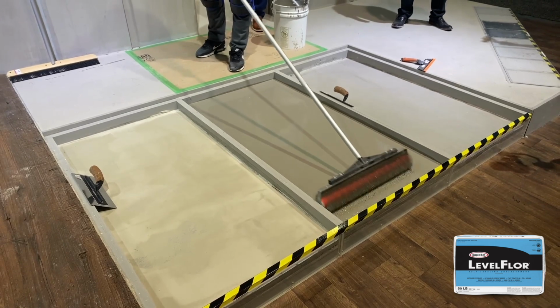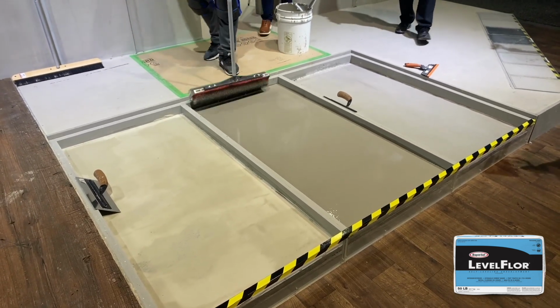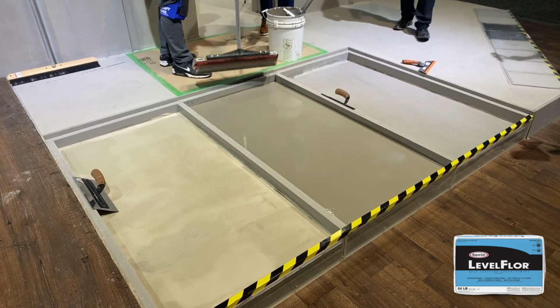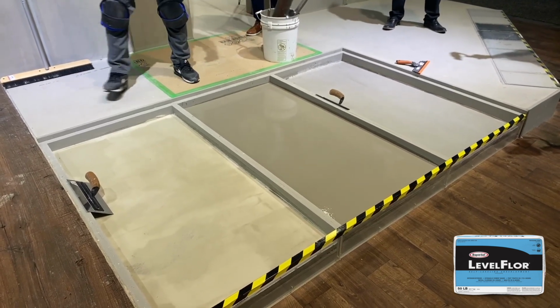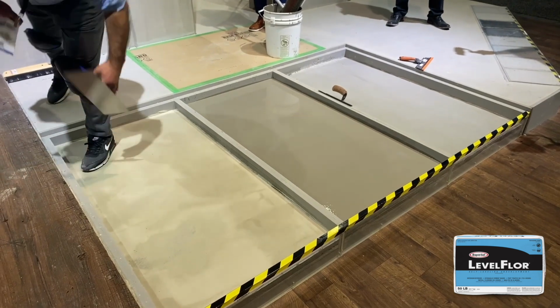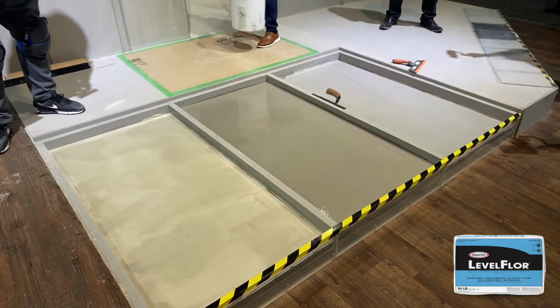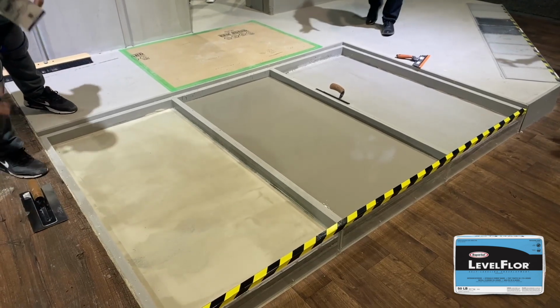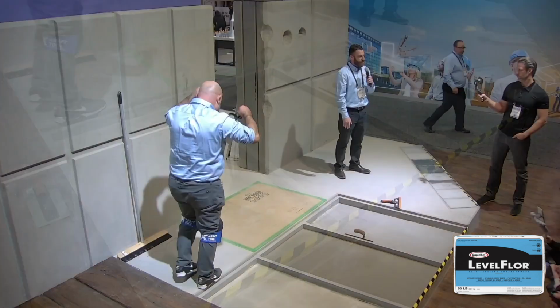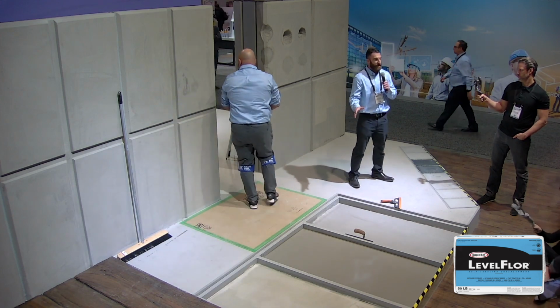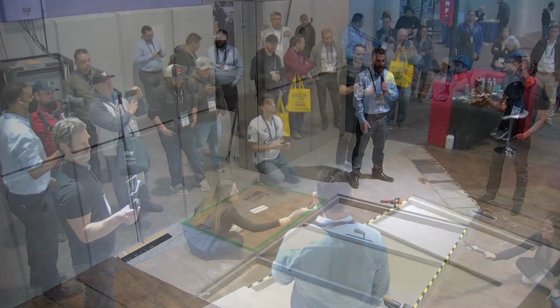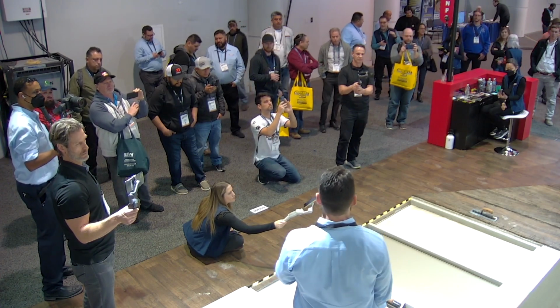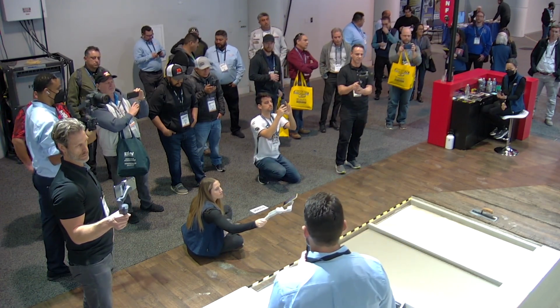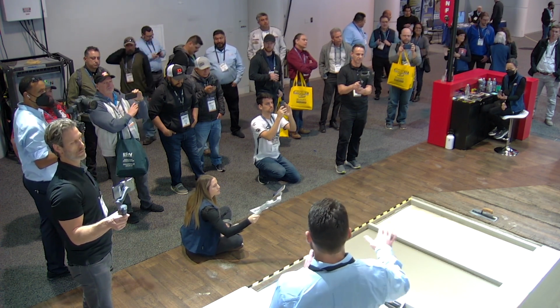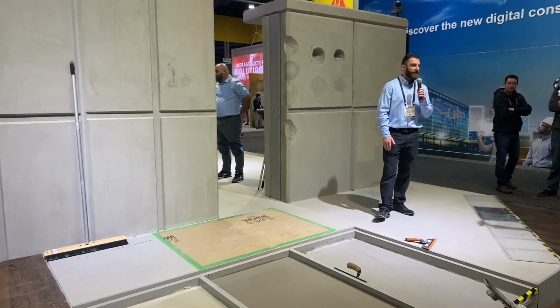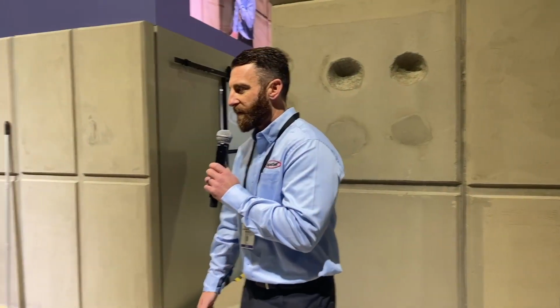So LevelFlor has about 20 minutes of working time and flow life. You can walk on it in about 3 to 4 hours. It gains structural strength of 3,000 PSI in 24 hours and 5,000 PSI at 28 days. So this contains self-curing technology. We don't have to come back and water cure this product. And then we can come back with our finished flooring. If it's a breathable flooring like ceramic tile, usually in just about 4 hours, you can put the tile on top. And for moisture-sensitive floors, usually about 16 hours is safe enough to come back with those types of floors. Of course, you'll want to check with your finished flooring manufacturer for substrate suitability.